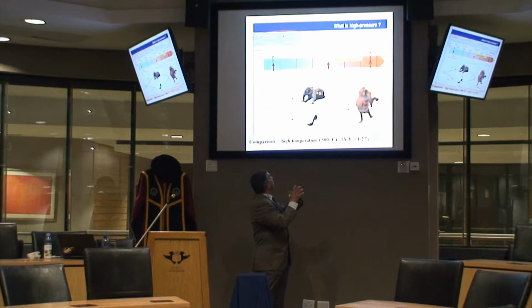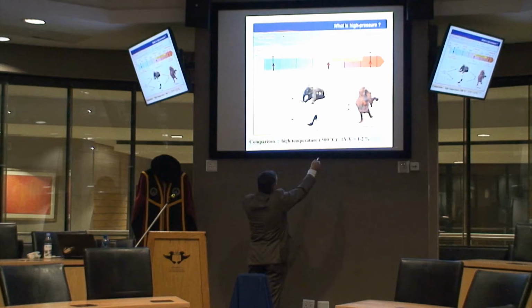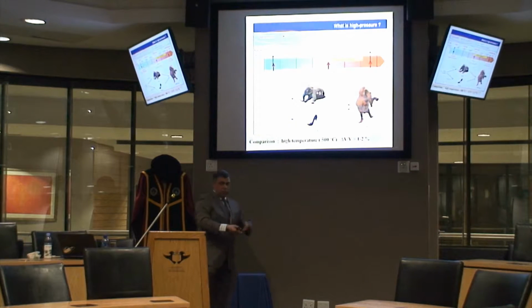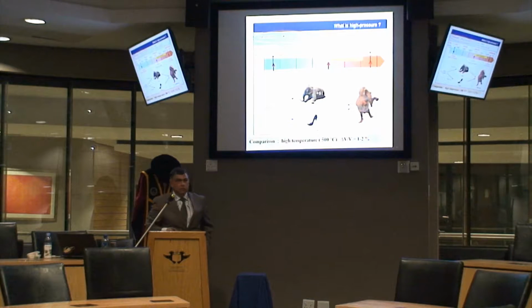Because when we apply pressure to a material, squeeze a material, we bring the atoms closer together, we change the volume, and in this range of 1 GPa to 100 GPa, 10,000 atmospheres to 1 million atmospheres, we can change the volume by as much as 10 to 25%. Okay? You can also change the volume of a material by cooling it or heating it, in which case it expands. But in that case, for comparison, if you were to heat the material to several hundred degrees, that would be the volume change, limited to something like 1 to 2%. So pressure can really wreak havoc within a solid.